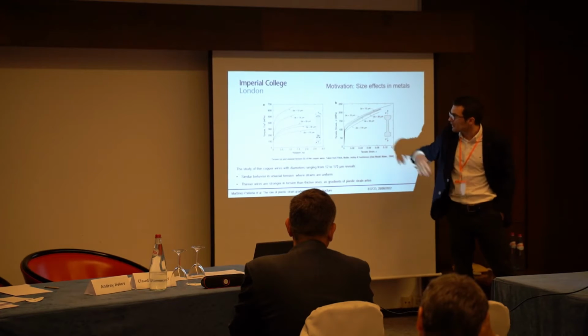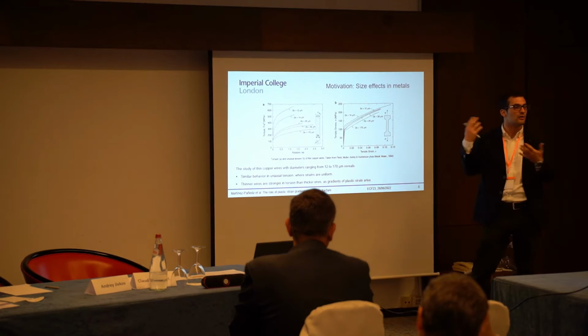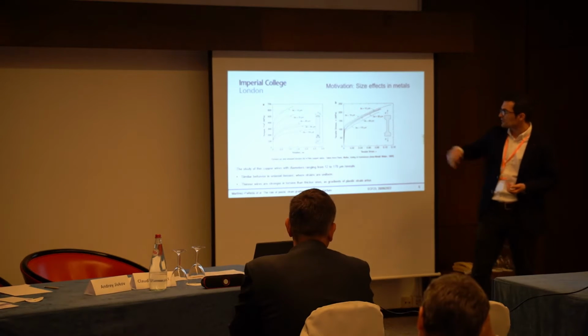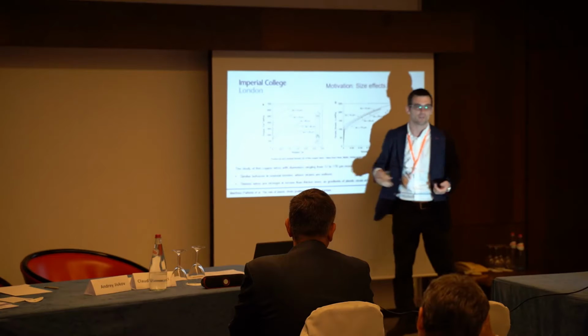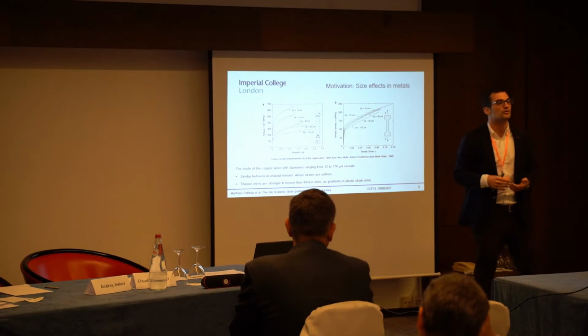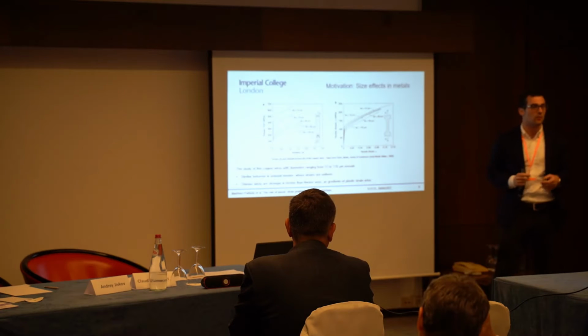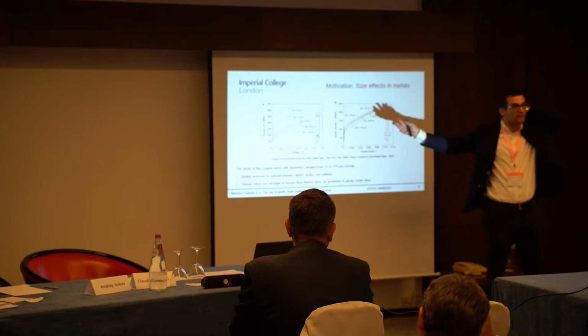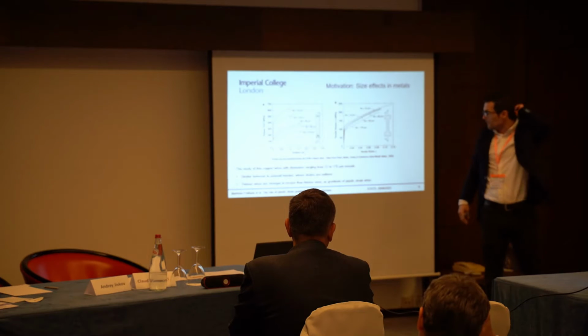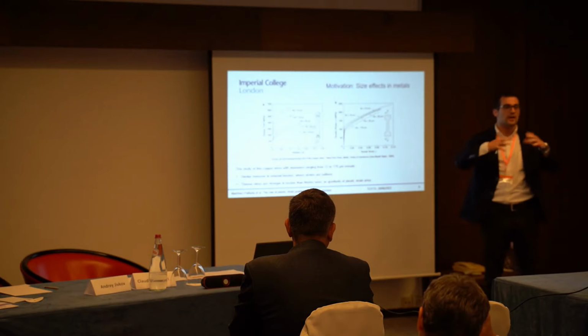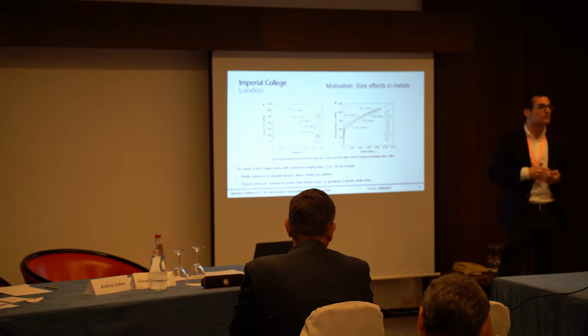However, whenever you have torsion, where you have gradients of plastic deformation and non-uniform plastic deformation, you see that those stress-strain curves no longer fall on top of each other, and you get a very significant strengthening effect with a decrease in the size of the wire. So you get this smaller-is-stronger effect that you observe in metals. And the reason you get this is associated with what we call geometrically necessary dislocations, GNDs.